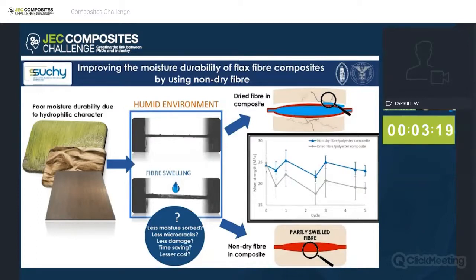But when this composite is exposed to a high moisture environment, it will definitely absorb water, resulting in cracks and damages, and eventually in the degradation of the properties of the whole composite. So compared to composites made of non-dry fiber, since the fiber already contains some amount of moisture and is already partly swelled, the effect of changing environmental conditions on the composite is possibly less. So composites made of non-dry fiber could have less moisture absorbed, less microcracks, less damage in the interface, and also